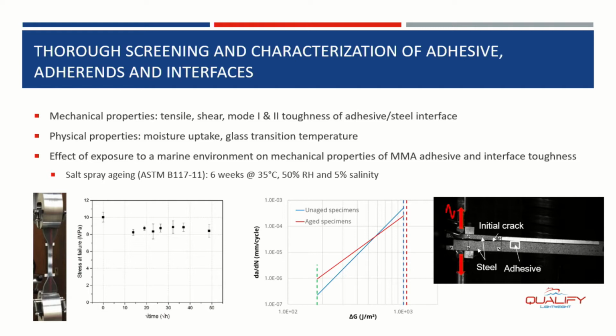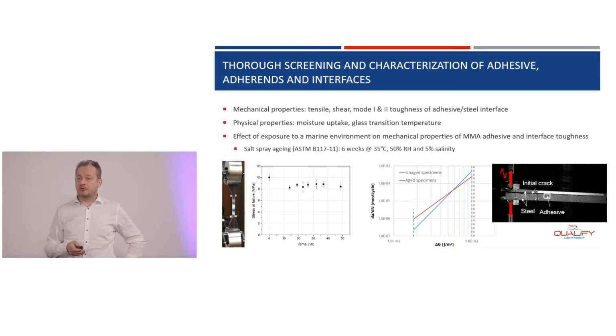If you look here at that graph, it shows you the tensile strength. You see that there is a small drop in the tensile strength of the MMA adhesive directly from the start, but not further affected by longer exposure. So that remains quite stable. The same was found for tensile modulus. For the ductility of the material, there was no clear influence of the exposure.